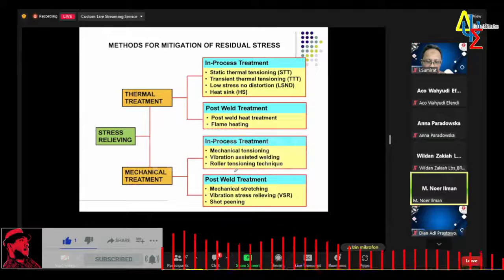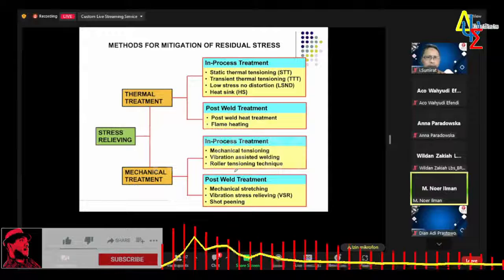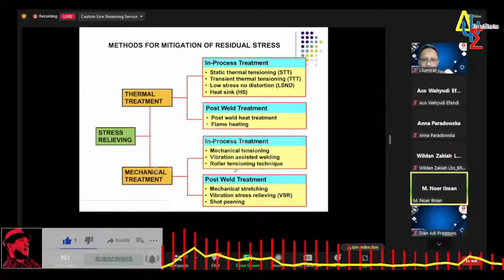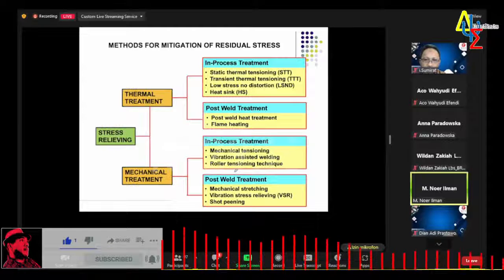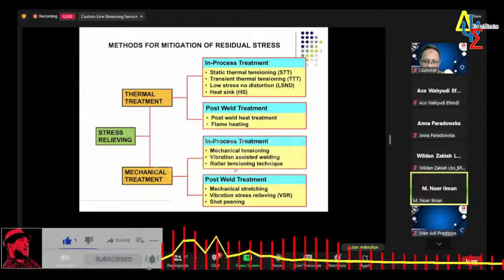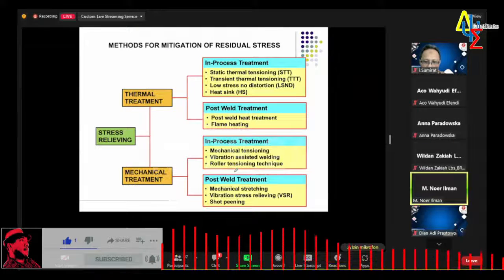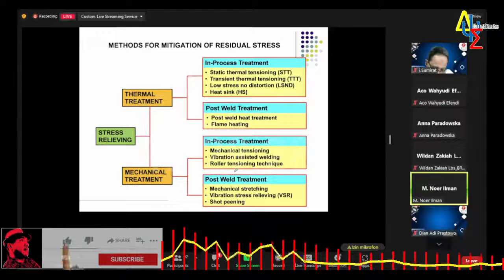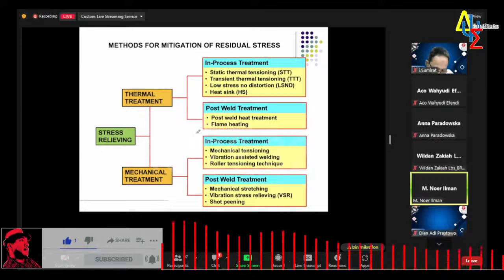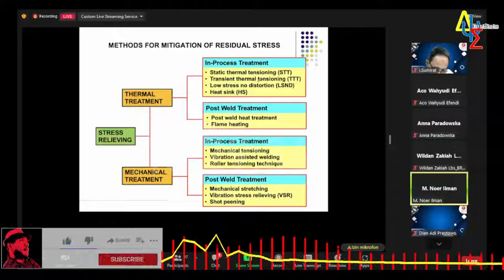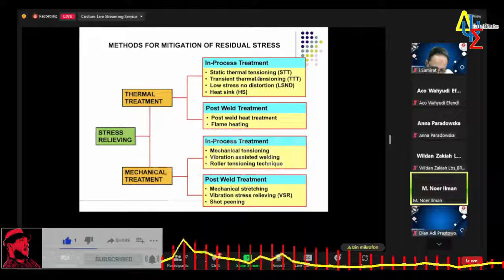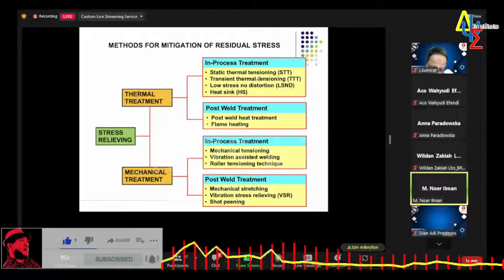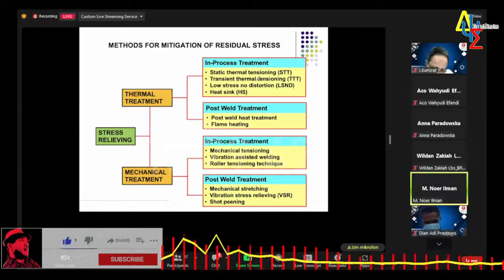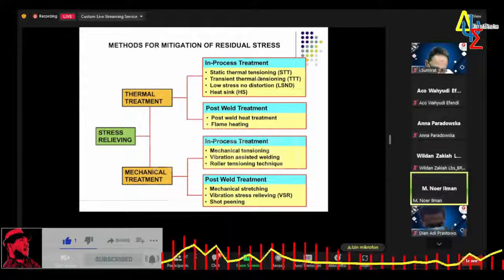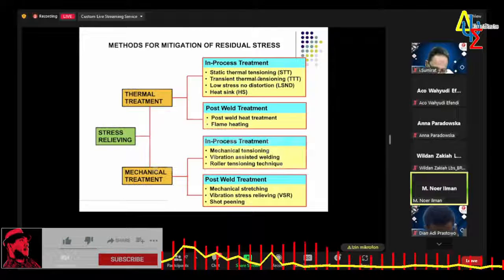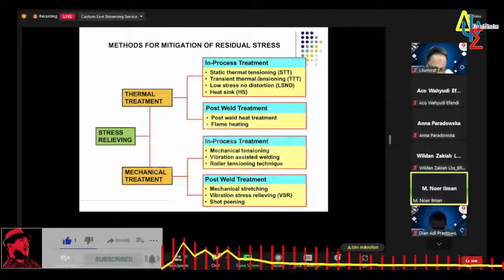Actually, stress relieving can be divided into two, which are thermal treatment and mechanical treatment. And this treatment can be performed during welding, or we can say in situ welding, or in-process treatment, and after welding, which is called post-weld treatment. So in thermal treatment, there are various residual stress mitigation techniques, such as static thermal tensioning, transient thermal tensioning, low stress no distortion, and heat sink, while post-weld treatment consists of post-weld heat treatment and flame heating.